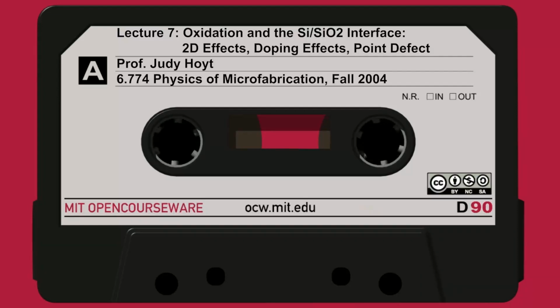So this is an equation that's been derived and that is used in SUPREM that gives reasonably good agreement with the experimental observations. So the viscosity as a function of stress is equal to the stress-independent viscosity, eta, which is a function of T, temperature, times this term with a shear stress in the oxide, so it's actually linearly dependent on the stress in the oxide.